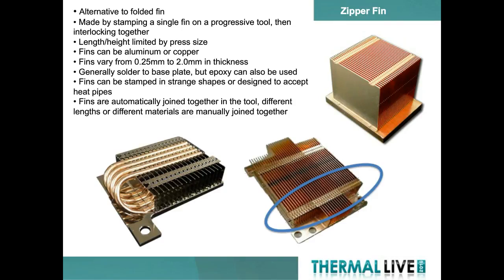The fins are typically bonded to a base using either epoxy or solder. One advantage of the zipper fins is they are stamped, so you can incorporate extra features in them like dimples for extra surface area. You can put in notches to provide clearance for other devices, or you can incorporate features to allow the use of a heat pipe. In the example that's shown there, the heat pipes are U-shaped. They come out of the base, curve up in the air, and connect to the top of the fins. It allows you to drive heat both into the base as well as into the tops of the fins to provide a more efficient thermal solution.